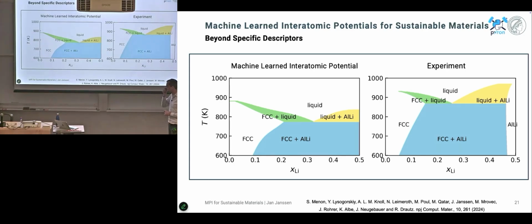Yes. So basically, each of these points, we can think about it like an MD trajectory at a specific temperature and specific concentration. And then one way to do it is thermodynamic integration over different methods. Right? So we can couple our lambda parameter between DFT and the machine learned potential. What we see in particular with the machine learning, so that's what we did previously, and that's still computationally very expensive because we have to once run the DFT thermodynamic integration.